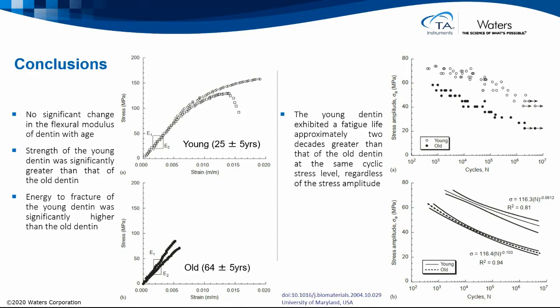And here we see that the modulus of the material is in the first section, but then as you increase the loading, the young tooth starts to continue, yields a little bit, and it goes to almost over 100 to 150 megapascals. But the older tooth down below, you'll see there's a couple examples there, 2 samples run. And interestingly, the modulus isn't significantly different between these. So it's not like it's harder. It's that it has less capacity to withstand the additional stress.